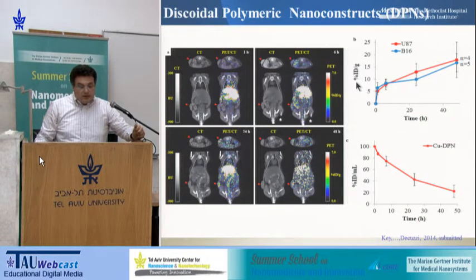When you get to the accumulation into the tumor, percentage of the injected dose per gram tissue, we are getting quite interesting values. We're getting up to 20% of the injected dose per gram tissue and even larger. And these are untargeted particles. These are untargeted particles that are using the same mechanism that I've described for the mesoporous silicon particles to accumulate and lodge into the vasculature.